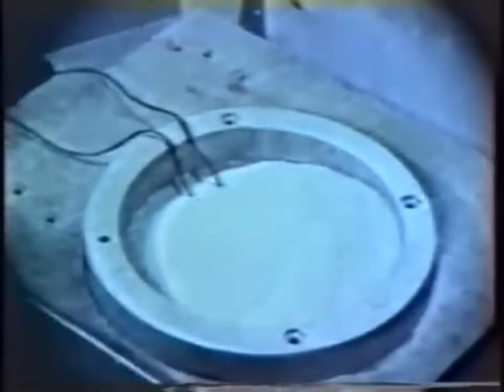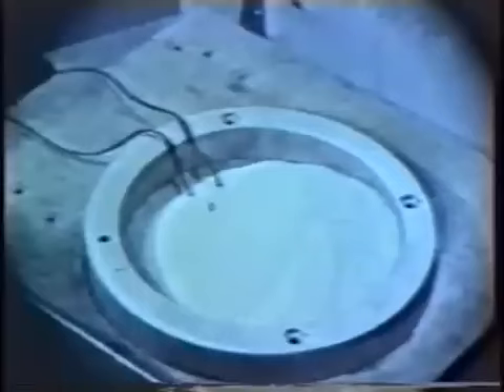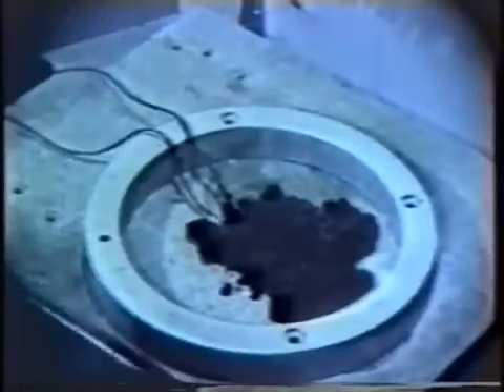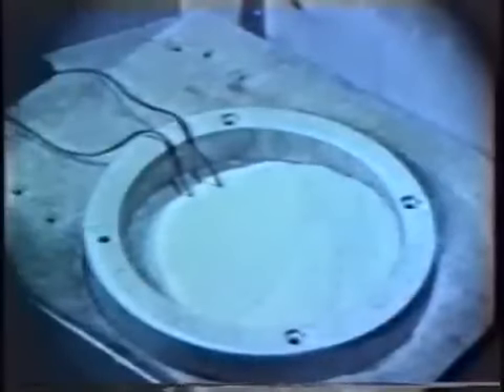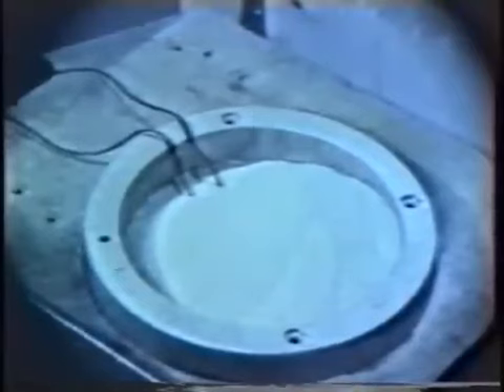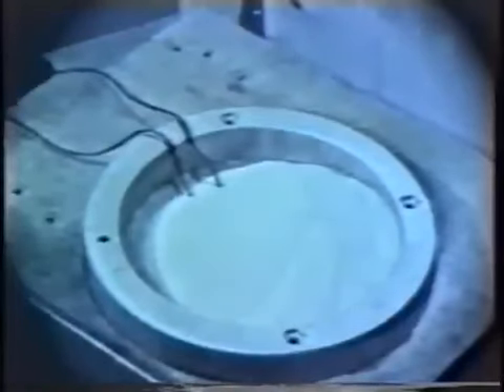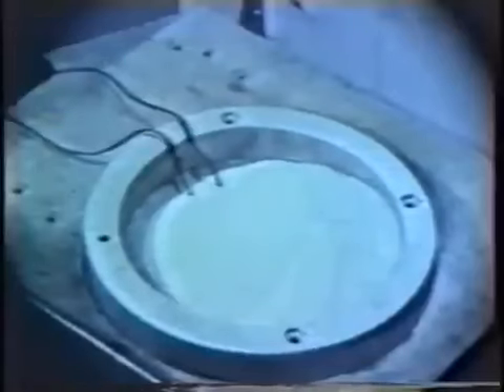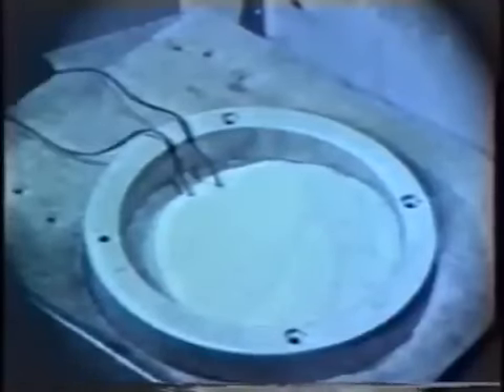One of the agents that was actually recommended here and was most effective was magnesium oxide sand. The magnesium oxide sand has a tendency to cover the fire, but as the fire continues to burn, the mag oxide sand would expand with it because it wasn't fused, and as a result it actually provided a better oxygen barrier than the other materials such as other metal turnings. Magnesium oxide sand didn't remove much heat, but apparently the other materials didn't either. So the magnesium oxide sand actually turned out to be the most effective way of extinguishing a plutonium metal fire.